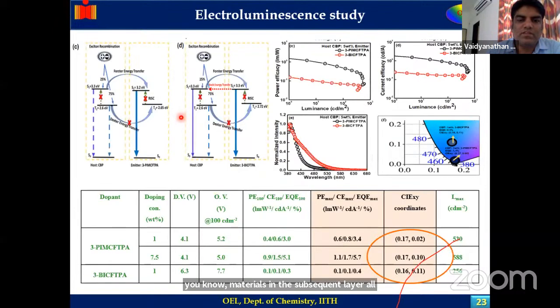So by using this type of architecture, we built the device with the electrode, cathode, and anode. We put the blue material here. We try to use all these materials in the subsequent layers, hole injection layer, electron transport layer, etc. What we found is that the electroluminescence shows very deep blue emission or UV emission. We get the CIE color coordinate of 0.02. It is very, very rarely reported in the literature.